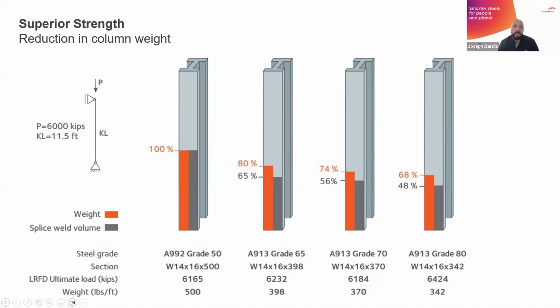But there's also a lot of hidden benefits that aren't that obvious when it comes to weight savings and using a smaller section size. So for the structural engineers out there, think about what a CJP weld looks like on a 14 by 500 versus a 14 by 342. That's a massive difference in weld size. So you're about half of the weld volume on a 14 by 342 relative to that 14 by 500. That is a lot of labor hours just going into that weld. If you've ever seen a CJP weld, you understand the massive scale of this, particularly if you're welding it in the field. That cost savings can be really, really large and impactful.